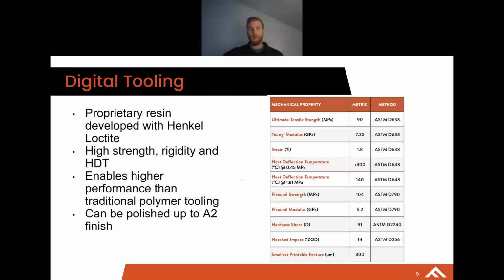Okay, so those 2 things, CKM plus the FLUXPRINT, have allowed Fortify to develop this digital tooling resin, which is a highly filled ceramic reinforced photopolymer. So it's an acrylate base that was developed by Henkel. So it's a proprietary base resin that they send to us. We mix in our ceramic fiber packet in order to increase the strength, rigidity, and most importantly, I think for molding is the HDT.